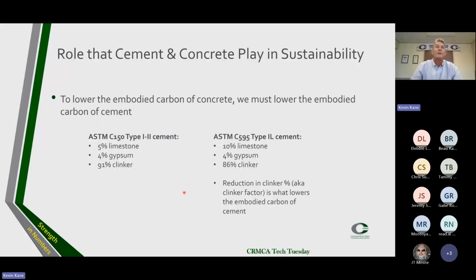Now, over here on the left, let's look at ASTM C150 Type I-II cement post, say, 2005. Post-2005, ASTM C150 Type 1-2 cement had 5% limestone, roughly 4% gypsum, and it was ground with roughly 91% clinker. ASTM C595 Type 1L cement has 10% limestone, or up to 15% limestone. Presently, most producers are around 10% limestone, and again, roughly 4% gypsum. And now we've reduced our clinker factor from 91% to 86%.